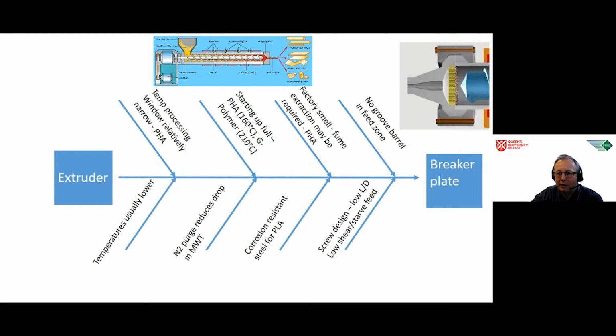So I've already said that there must be no stagnant areas such as groove feed. So groove feed extruders are not recommended for biomaterials. Some biomaterials such as PLA may be harsher on certain steels if they're not corrosion resistant. So if we are moving to PLA, maybe more corrosion resistant steel for screws and barrels may be required. And in some cases, there will be specialist protocols for starting up extruders to minimize degradation at the start, and for shutting down extruders to eliminate all biomaterials. So there are just new protocols that must be looked at.